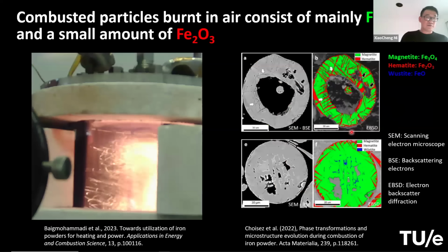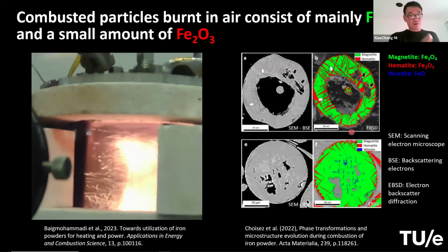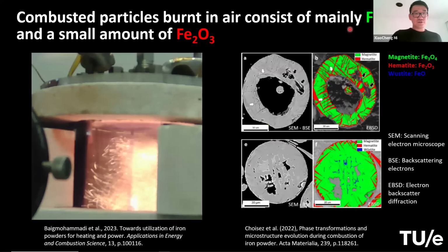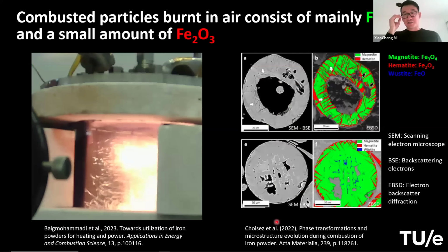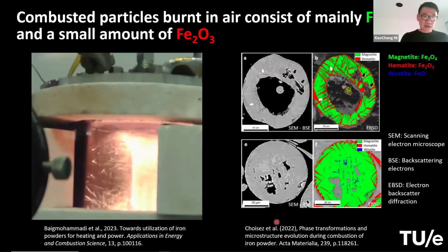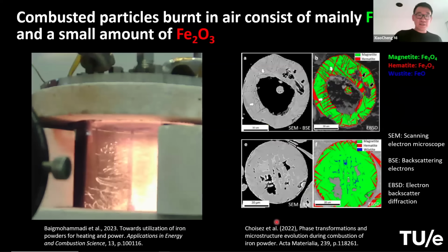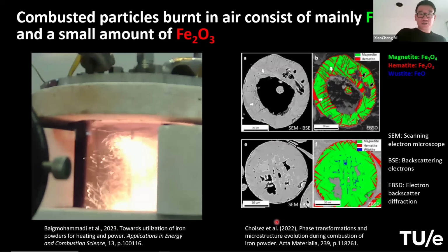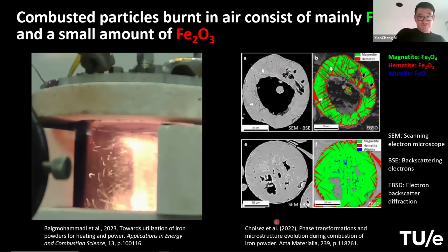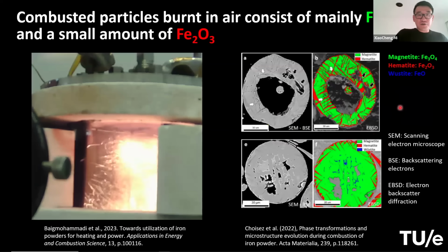And this is some basic understanding. We burn these iron particles in our lab burner, and we can collect the product and do some further material characterizations. So these are some cross-sectional EBSD, electron backscatter diffraction, images that show the phase distribution across the particle cross-section. The green area shows magnetite.